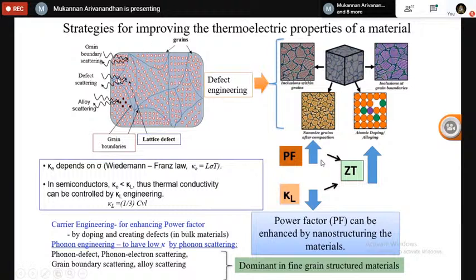These defects act as phonon scattering centers. These defects may effectively scatter the phonons, and by effectively scattering the phonons, one can control the phonon mean free path. If you control the phonon mean free path, you can control the lattice part of thermal conductivity. By controlling the lattice part of thermal conductivity, you can have a high figure of merit. And by increasing the figure of merit, you can have a high conversion efficiency. So that is the idea.